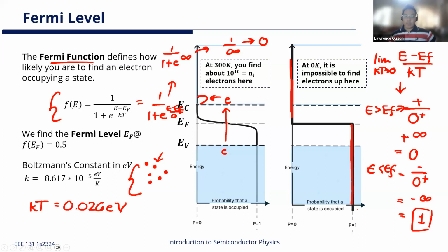So I just showed you guys how we got this flat band, no? But as T approaches 0, what I want you guys to notice is this one is flat 0, and this other one is a flat 1, right? So then at 0 Kelvin, it's not degrees, it is impossible to find electrons on the conduction band, and all of them would be in the valence band, no?